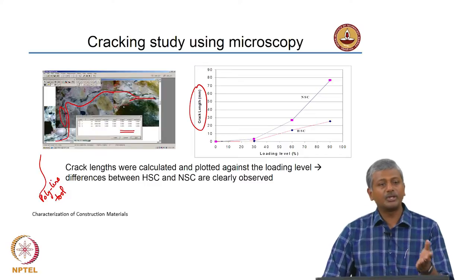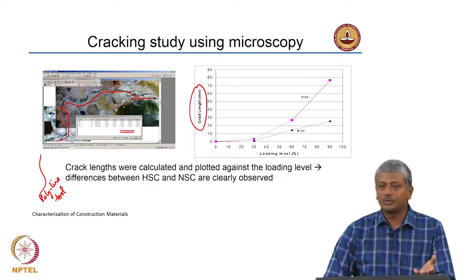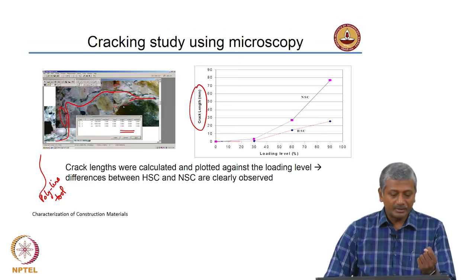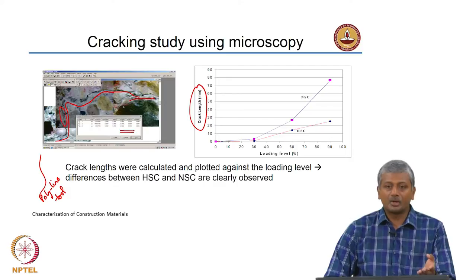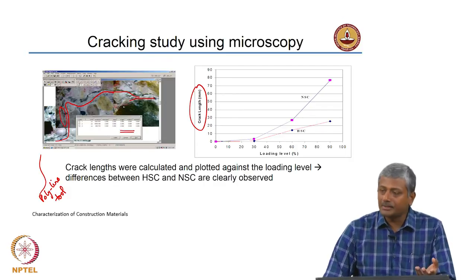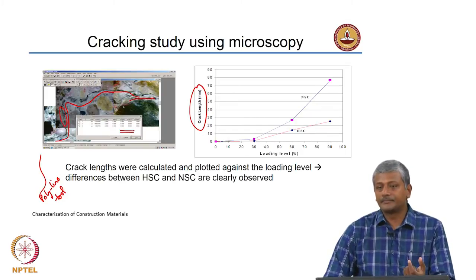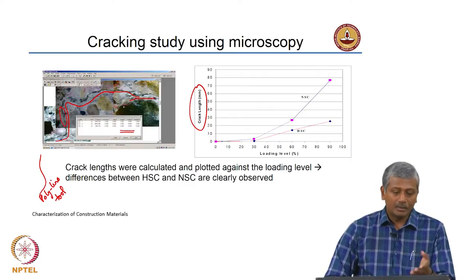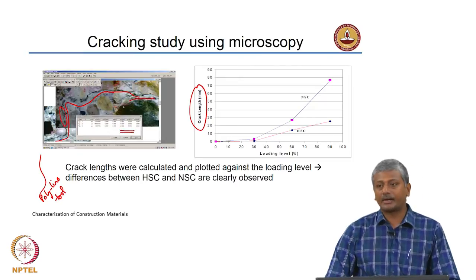You need to have some sort of calibration to ensure that you can ascertain the actual length of the phases. Calibration in optical microscopy can be quite easily done by imaging at the same magnification a scale bar or ruler, and then you can apply the same length to the number of pixels represented by the polyline tool to convert that to the actual crack length.